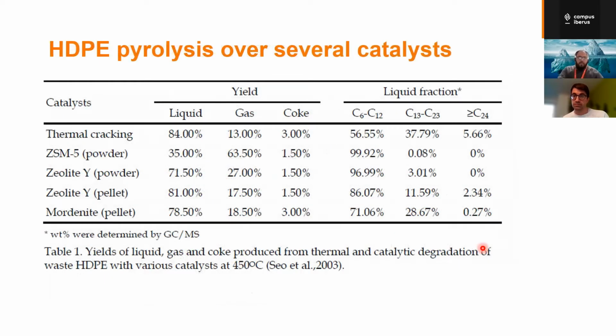If I try to show you here in this table, this is basically the pyrolysis of polyethylene over different catalysts, and how the liquid yield and the liquid fraction look like. So if I take a look at the thermal cracking, which is without any catalyst, the liquid yield is 84%, gas is 13%, coke is 3%, and your liquid fraction contains a lot of C6 to C12, but also quite a lot of C13 to C23.